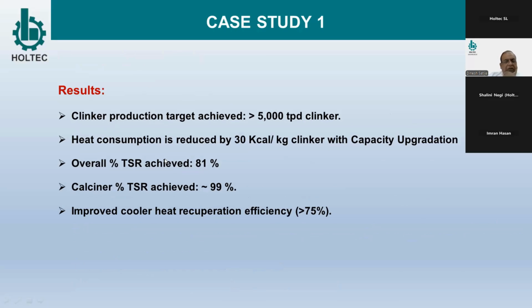So finally, after completion of the project, the clinker production achieved was 5,000 TPD against 4,850. And there was a reduction in heat consumption, primarily due to the capacity increase and the new, more efficient cooler. Overall TSR achieved was 81%, and calciner TSR replacement was 99%. And the cooler thermal efficiency, of course, has increased to 75%.